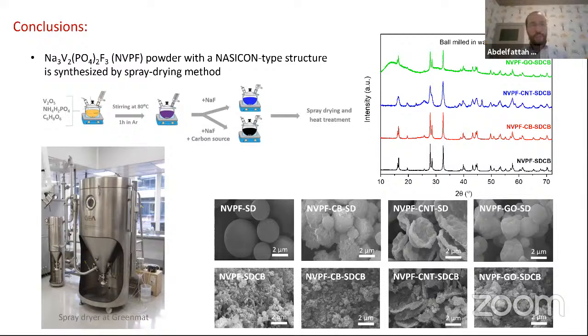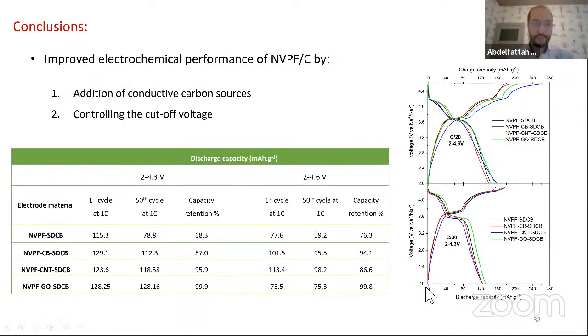So as a conclusion, in this work we succeeded in preparing the pure materials, either without carbon or with carbon black, carbon nanotubes and graphene oxide, by using the spray drying method. We can see that the source of the carbon has a great effect on the morphology. And also after grinding, the particle size decreased dramatically, except for the one with carbon nanotubes.